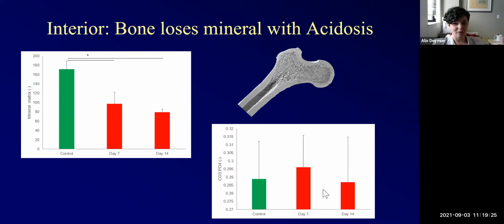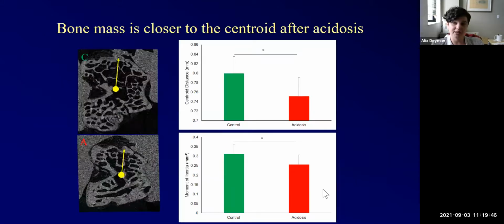So if indeed my cells are doing things, which this seems to suggest, and I'm getting some sort of physiochemical response, which my exterior measurements seem to suggest, maybe I'm going to get a change in the shape and size of my bone. So the first thing we did after Raman was to go ahead and do micro-CT, which is microcomputed tomography, and essentially gives us cross-sections or 3D images of our bone structure. And what we ended up finding was that having acidosis, so 14 days of soda drinking, caused a significant change in the shape of the bone. They were much more compact, smaller, and they had a lower moment of inertia.